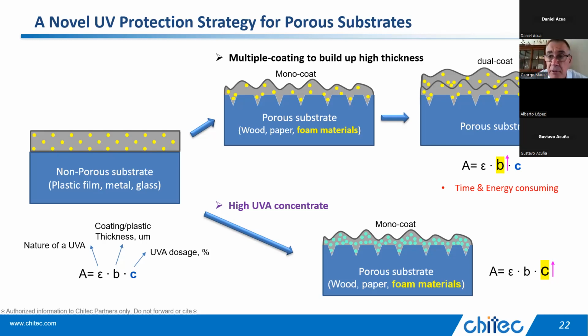If you were to try and put Tinuvin 1130 in at 10%, or since that's got a higher molecular weight, you might have to go to 15%, then you would hurt the film properties and it wouldn't be a good coating. Even though you might get very concentrated UV absorber, your film wouldn't be good. So what you would have to do is put it in at 3%, but then put on several layers in order to get as much UV absorbing capability out of your film.